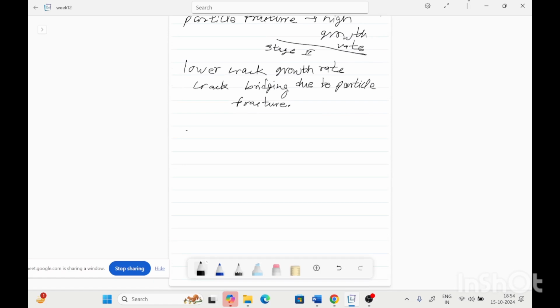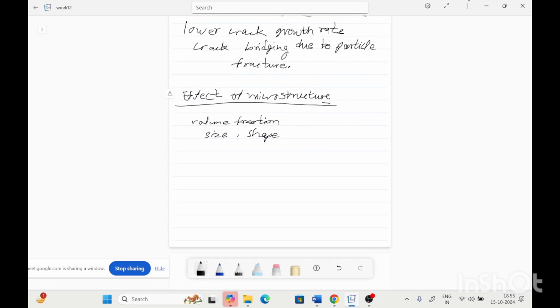And if we see the effect of microstructure, so the microstructure of the composite will differ because of the particle nature, the volume fraction of particle, and size and shape. So this effect comes because of the volume fraction, size and shape of the particle. So if the volume fraction is high, the fatigue life will also increase.